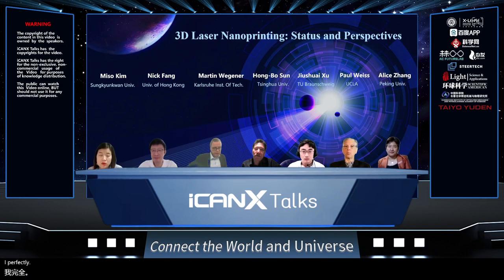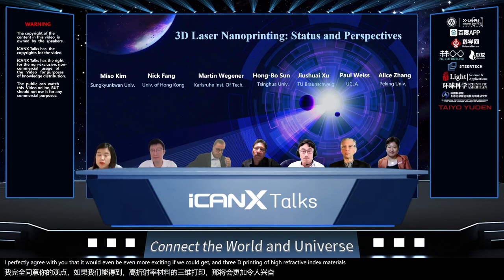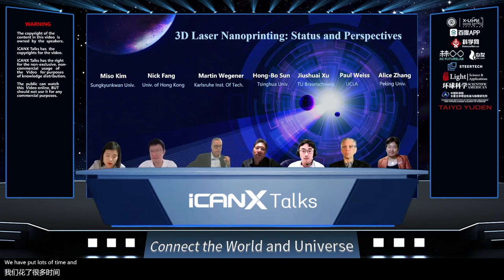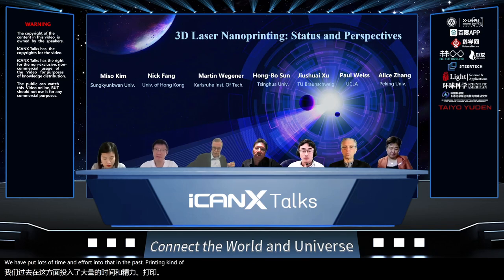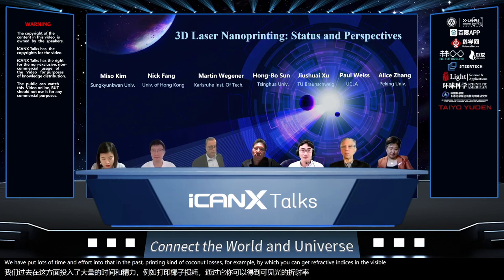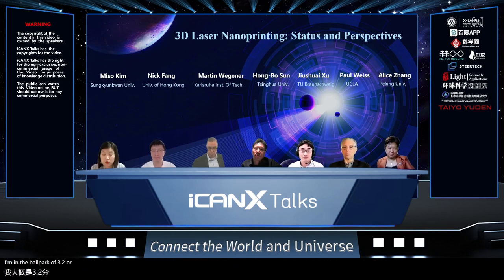I perfectly agree with you that it would be even more exciting if we could get 3D printing of high refractive index materials. We have put lots of time and effort into that in the past, printing chalcogenide glasses, for example, by which you can get refractive indices in the visible in the ballpark of 3.2 or so. It's close to silicon. The issue is that, as photoresists, they are much more nasty. Actually, some of the stuff you use there is poisonous. That's one thing that I think has inhibited spreading this technology a lot.